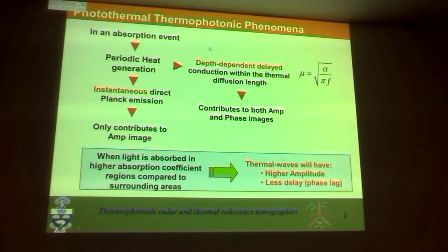If, on the other hand, the absorption coefficient is very low, then I get heating all the way to the body of the sample. The central mass of the heat of the thermal wave field is somewhere down there, so it takes more time to come out, so the phase shift is longer. So phase and amplitude are there.